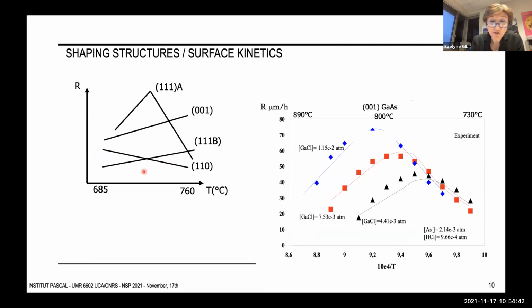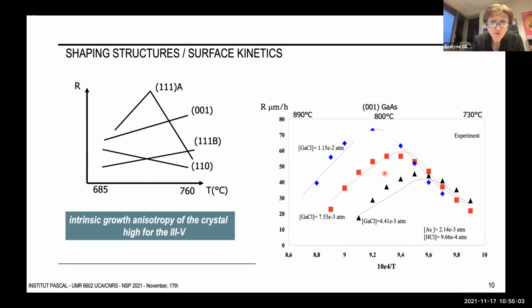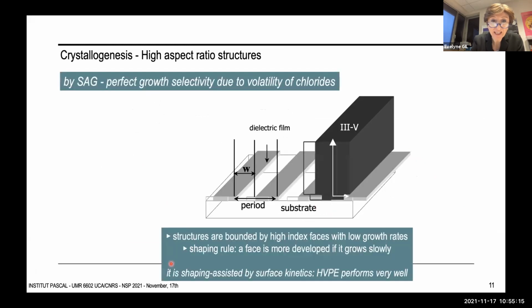So it is possible to shape various 3D, three-dimensional morphologies by taking advantage of the fast or slow development of these facets, knowing that the growth rate can be widely varied with the temperature, as you can see here or here, or with the vapor phase. So that means that the intrinsic growth anisotropy of a crystal that is very high for the III-Vs can actually be fully exploited by HVPE to grow various aspect ratio structures in a few minutes that you can obtain by selective area growth on a masked substrate.